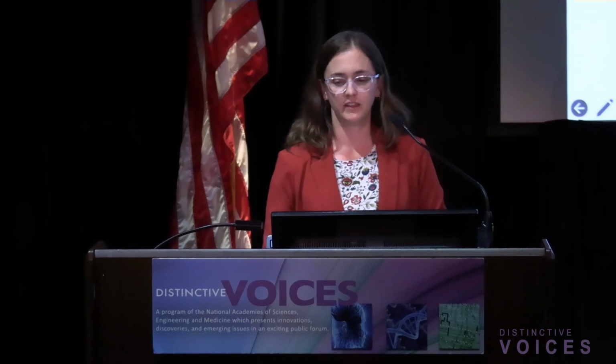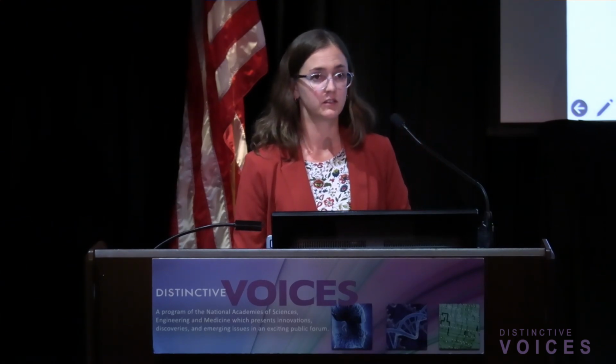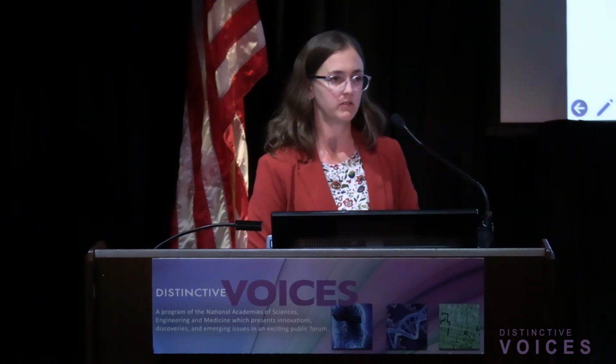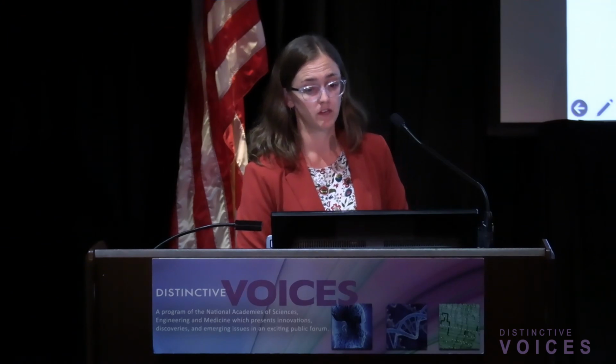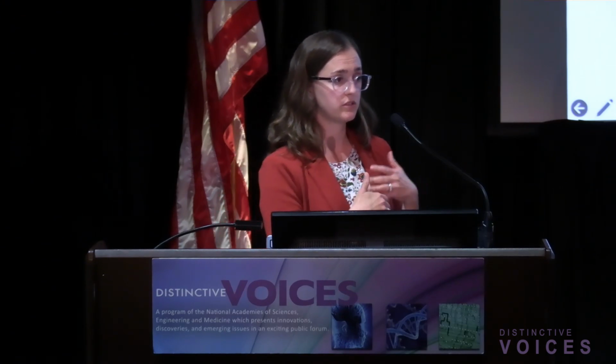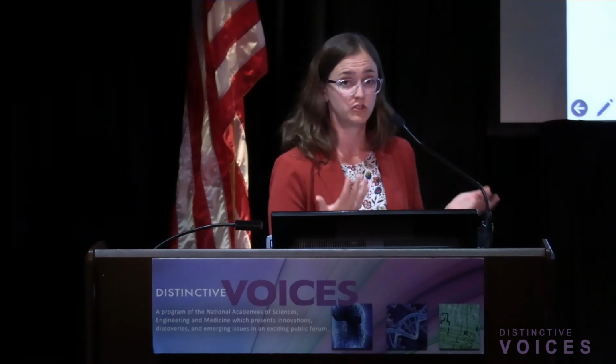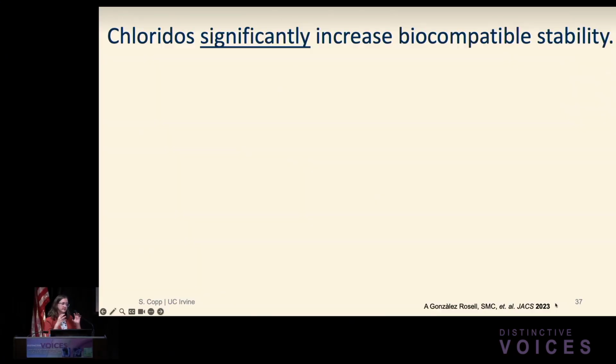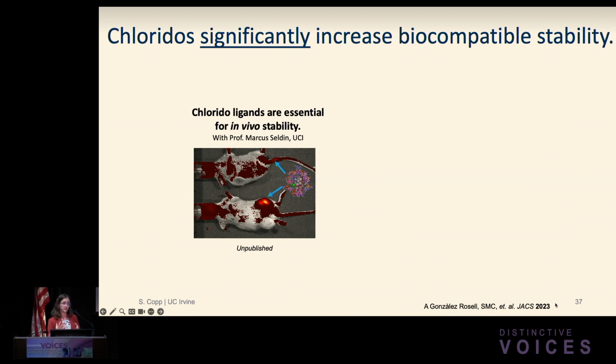But there was also an unintended discovery here. And that was related to the fact that these chlorides were found to make the nanoclusters much more biocompatible. So we found over the course of studying this cluster for almost 2 years that this chloride-stabilized AgDNA was much more stable in a variety of different solutions than many of the ones we studied. And we started to wonder if maybe the presence of the chlorides was important for that. And in fact, the stability of this cluster was really significant.